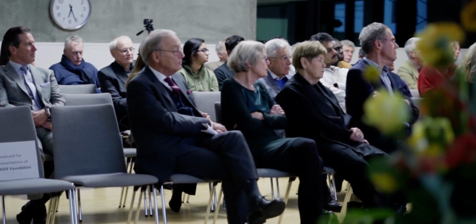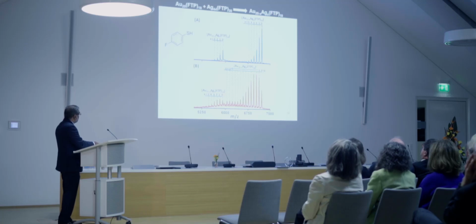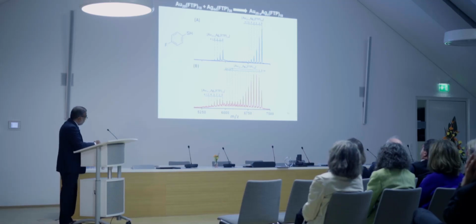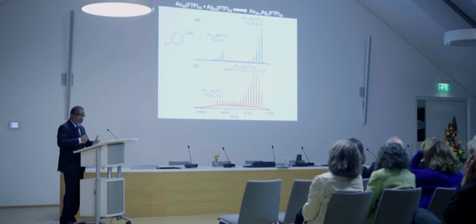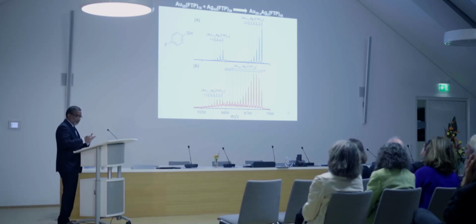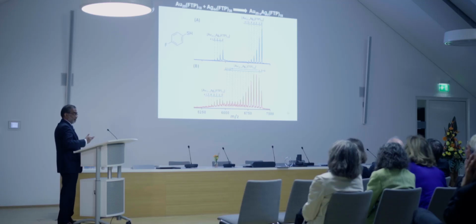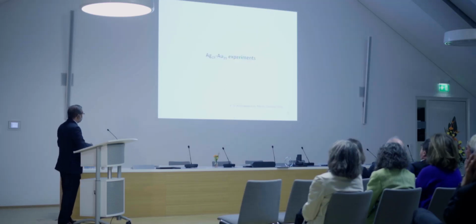Now, a little later, after 1 minute, these peaks go up in intensity. That peak will come down in intensity. Later on, this will be completely gone. Another kind of composition will emerge. So I am doing molecular reactions of nanoparticles with atomic precision.